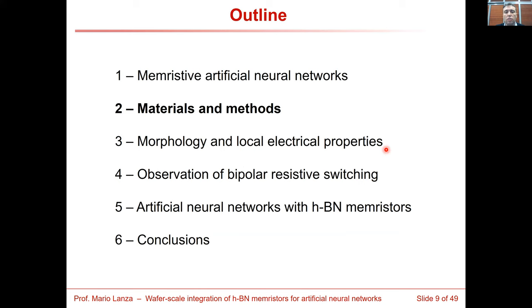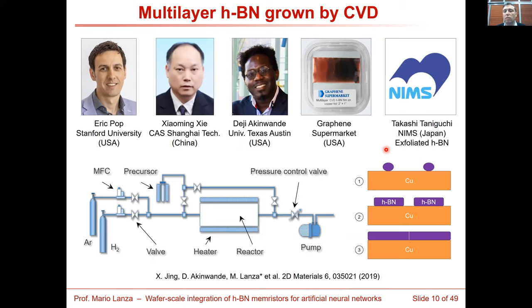In our group we use multi-layer hexagonal boron nitride (h-BN) grown by chemical vapor deposition. We have received materials from collaborators at Stanford, UT Austin, and Shanghai, purchased from Graphene Supermarket, and obtained exfoliated samples from NIMS for comparison with perfect material. In the CVD process, seeds are deposited at high temperature, they nucleate and grow into a continuous film that may have grain boundaries. Single-crystalline material has been achieved for monolayers, but for multi-layer it remains more difficult.